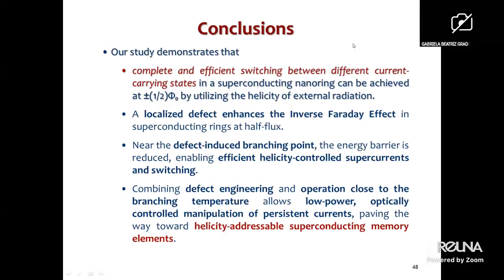Okay, yes. And about these defect possibilities, the defect can let you tune, and that's something you are already calculating. But I guess experiments will be very, very difficult. Yes. The defect does not create any significant problems in calculations. That's why I presented it here: it simply softens the free energy barrier between the 0 and 1 modes, and that allows speeding up the switch between the 0 and 1 modes. Basically, if we have quite slow switching, then we simply engineer the system by including a defect there, and then the switching time will decrease, as I showed in one of the last slides. Right. But of course, probably the experiments will be much more difficult.